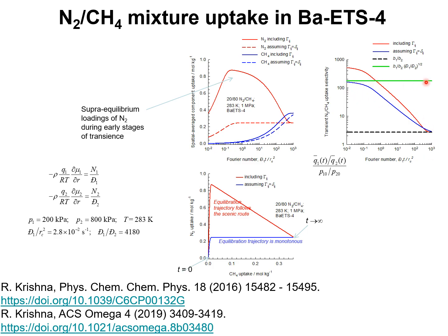The green line are calculations using a kinetic selectivity that is defined by the ratio of the Langmuir constants B1 to B2 and the square root of the diffusivities. This is the kinetic selectivity that is commonly defined in the literature. We note that the Maxwell-Stefan diffusion model